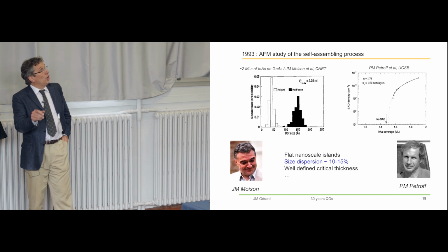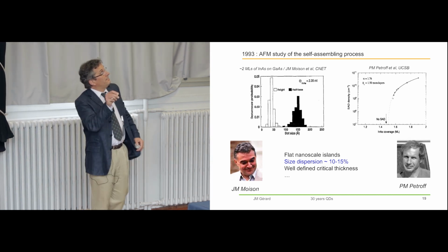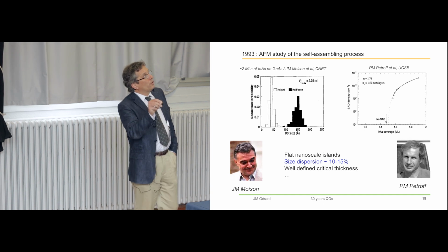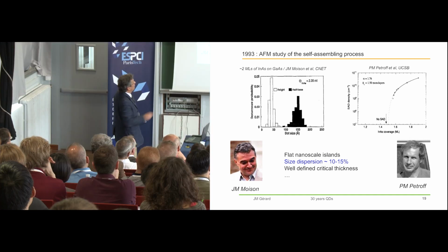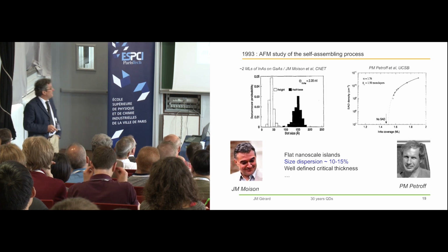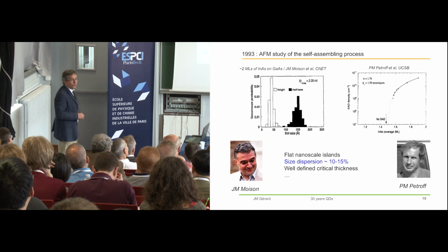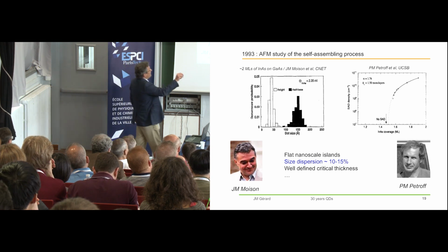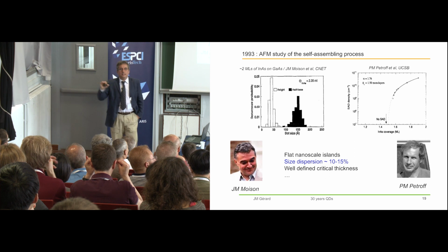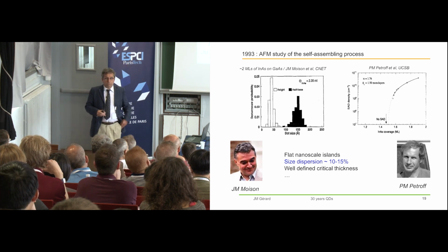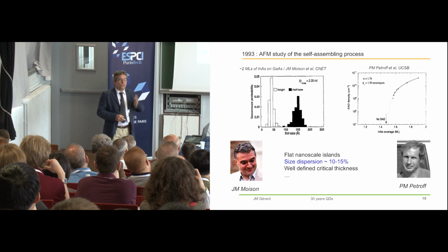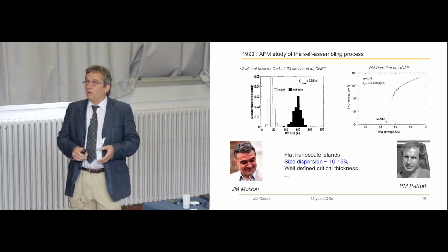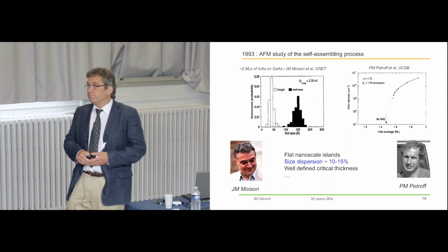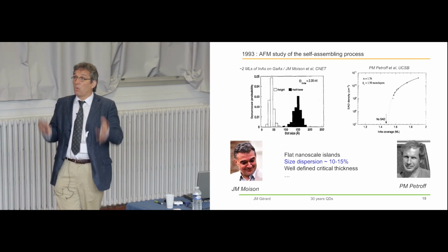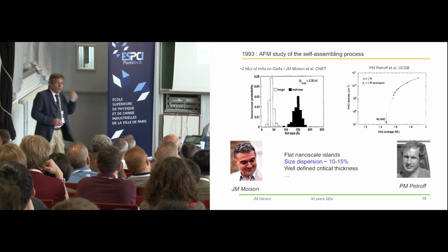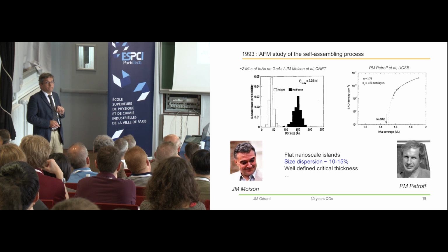So at that time, for instance, size histograms were published here, and it could be shown also in Santa Barbara that the critical thickness is very well defined. What do we learn also from that? We learn that the size dispersion is around 10% plus, which is, in fact, large. But it is good compared to what you get simply playing with lithography and etching. So nature gives you something that is more homogeneous than nanofabrication when you speak about objects in the 10 nanometer range.